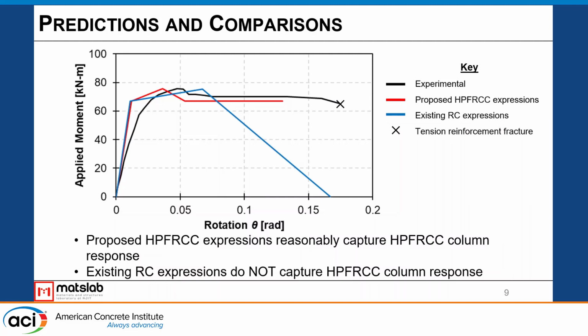And what we can see right off the bat is that our proposed HPFRCC expressions can reasonably capture the behavior of the experimental that we're seeing. And what we can also see is that the existing reinforced concrete expressions don't adequately capture the experimental behavior. Like we had seen in that contour plot before, we still have considerable residual strength after we reach the nominal capacity of the column up till failure. Whereas in the reinforced concrete expressions, what typically happens is once we reach that nominal capacity, we have continued degradation, typically associated with rebar buckling and crushing, and then we typically ignore the residual strength of these columns. So we're not really capturing and taking advantage of these ductile materials if we were to use existing reinforced concrete expressions.